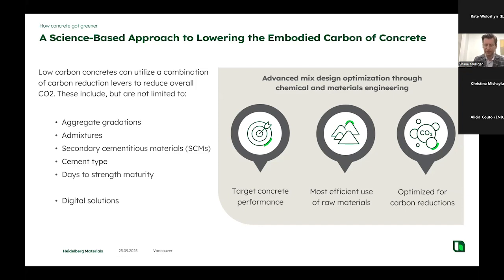to allow us to pull out some of that cementitious content, increase the amount of SCMs we're using relative to cement, and make a relatively sizable impact on reducing the carbon intensity of the concrete. But that's not always an option. A lot of times we're actually seeing schedule demands requiring us to go the other way, where we're looking at higher early strength concrete applications in high rises and suspended slab type applications. And we can still design lower carbon mixes to meet those performance targets.